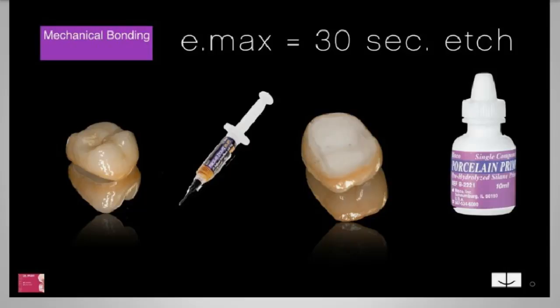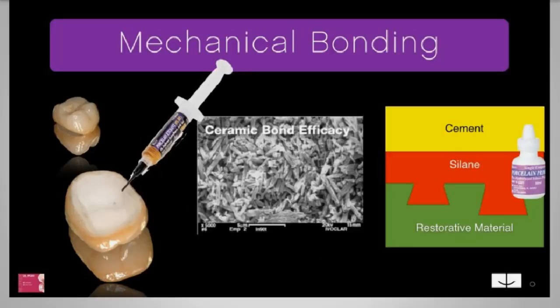Now, this picture that you see, let me show you here with my cursor, this here is over-etched. That is too much. That is too frosty. You don't want it that frosty. You want it just a little less frosty than this. It's 30 seconds and that's it. There are different studies that show that you can actually create weakness in the Emax if you over-etch it. So you just want to do it at 30 seconds. Okay? So that's the micromechanical, because it creates this lattice formation that the silane can fill in and create that really strong bond to the ceramic.